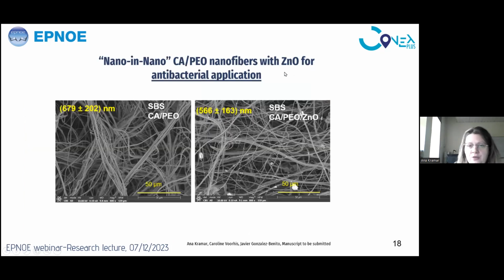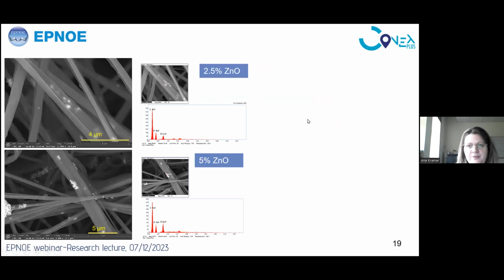Regarding the potential application of these fibers, besides, as you saw, a tremendous absorption capacity, we also tried to include some antimicrobial components. So we decided to use zinc oxide nanoparticles for antibacterial application. And here you can see we successfully incorporated zinc oxide into cellulose acetate polyethylene oxide composite nanofibers, and we even obtained slightly finer, thinner fibers. We used EDX to confirm that it is zinc oxide. Here you can see we used 2.5 and 5% of nanoparticles in the nanofibers.